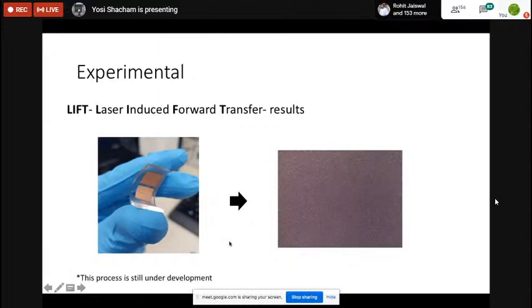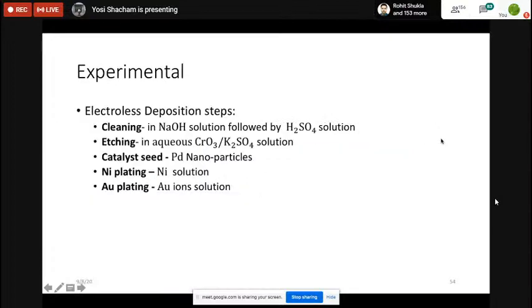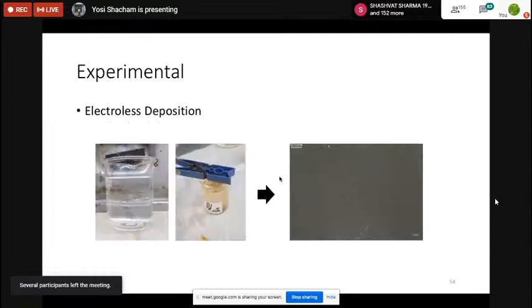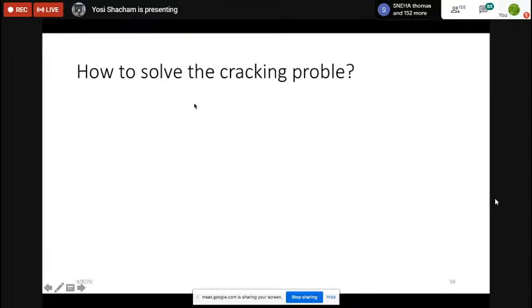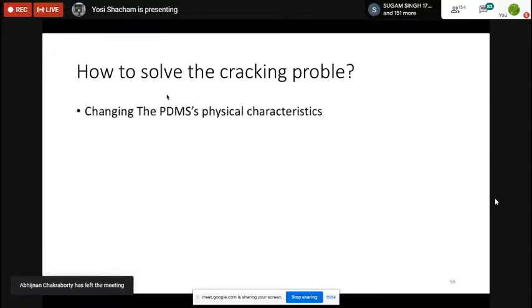But you know, we are a university; anytime we solve a problem, then we look for another problem. We still have this problem of cracking of the normal process. So we clean, we etch, we catalyze the seed, we do electroless plating on top of it. And electroless plating on top of it solves a lot of the problems, because we can do some combination of a softer material, but we still had some cracks. This is electroless deposition on PDMS; you see we got no defects, but we still want to understand why we get cracks in the old problem, because we really like to do evaporation on plastic because it's commercial technology.